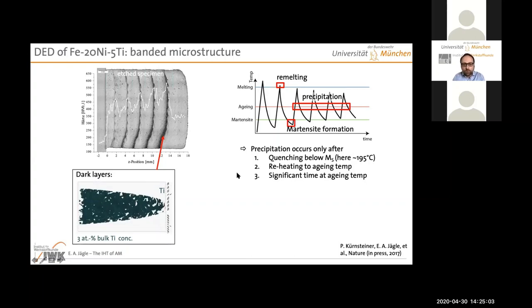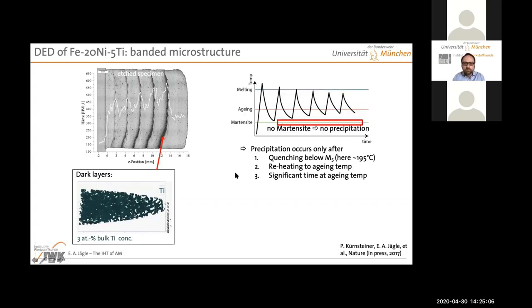However, what could happen is that you choose your process parameters such that you put so much energy into the sample that the quenching never reaches martensite start temperatures. So you stay in the austenite basically always. And therefore the intrinsic heat treatment is not effective because you're just cycling your austenite. There is no precipitation going on. So in order to get precipitation at all, you need 2 phase transformations. First, you need to quench down and allow martensite to occur. And secondly, you need this reheating, which then triggers the precipitation inside the martensite.